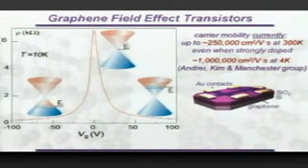So the consequence of this extremely fast propagation of those electrons is that if you make a transistor out of this material, and it's quite easy to make a transistor out of this material, it would work extremely fast and at very high frequencies. The figure of merit there is called the mobility, which is how much scattering your electron experiences as it moves. The typical mobility which we can achieve in this material is a quarter of a million. Of course, it doesn't tell you much until we compare it to something. This figure for a typical silicon transistor in most of the integrated circuits in the microprocessors would be 1,000, and in the best transistors which are in your mobile phones would be 50,000. So we are orders of magnitude better than the best transistors which are available to us at the moment.